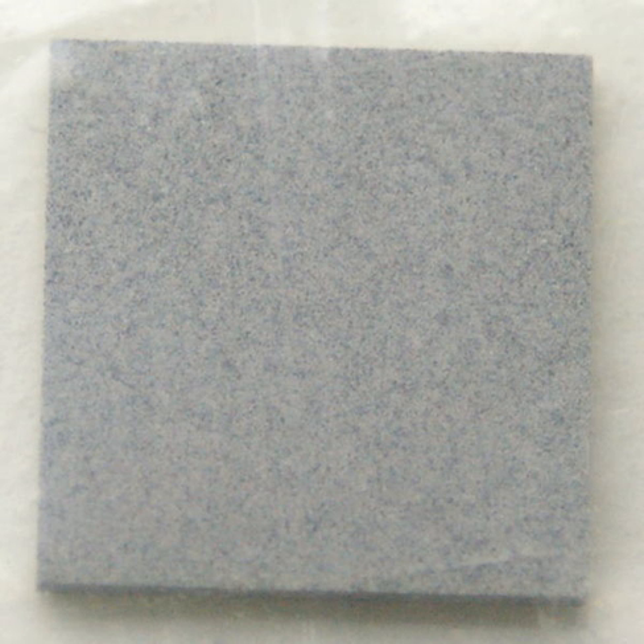It can also be prepared by the diamide route. SiCl4 + 6NH3 → Si(NH2)4 + 4NH4Cl at 0 degrees Celsius. 3Si(NH2)4 → Si3N4 + N2 + 3H2 (g) at 1000 degrees. Carbothermal reduction of silicon dioxide in nitrogen atmosphere at 1400 to 1450 degrees Celsius has also been examined.